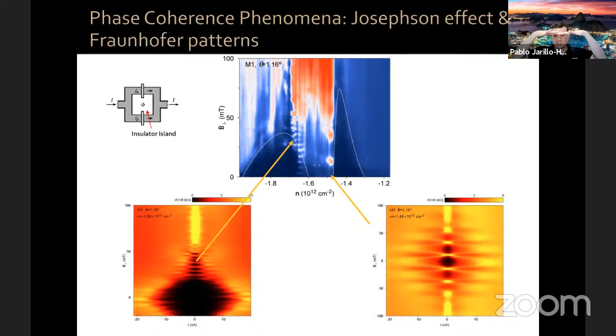We have a graphene sheet, we cut it in two pieces, and we put one piece on top of the other, and we rotate on purpose 1.1 degrees so that we make these devices. And we have a very high success yield for this, meaning in my group, not all groups are the same, we have a little bit more experience, but in my group, over 50% of the devices that we assemble have the angle between 1 and 1.2 degrees and therefore exhibit superconductivity, et cetera. That's over 50% of the devices. That's a much higher success yield than for many other projects that I have worked on.